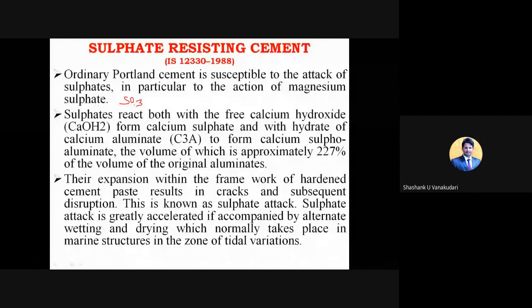And how does that sulfate attack get caused? The sulfates react with the free calcium hydroxide, that is SO3 reacts with free calcium hydroxide. Free calcium hydroxide in the sense along with the CSH gel, which comes out and is not at all useful. That's Ca(OH)2, calcium hydroxide, right? After the flowchart at the end, you have seen this product, right? So when sulfates react with this calcium hydroxide they form calcium sulfate, right? And with hydrate of calcium aluminate they form calcium sulfoaluminate.